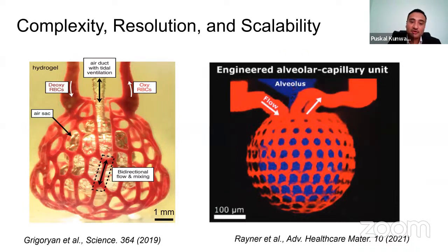Now, there's another approach, which is direct laser writing. So basically here you have a collagen material, and you use direct laser writing to create this alveolus structure. Now the size is very, very small, 100 micrometers. So this definitely gives the size of one air sac within the alveolus. Now, this is a serial scanning based approach. So to print this small structure, it takes hours already. Scaling this up is extremely time consuming.